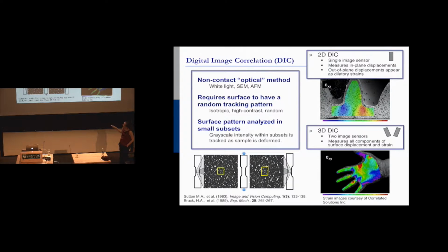So it starts out square, and then as you pull and you continue to take images through the test, the box is going to change its shape. And you do that for many, many boxes that are overlapping, and you minimize some cross-correlation functions, and you can get a very, very accurate full-field strain on the surface of the specimen. And so if you do 2D, that's one image and one specimen and one camera on the specimen. The problem with 2D is everything has to be planar, because the minute that you move your specimen towards the camera, the dots look bigger, but I haven't actually applied any strain, right? It's just a rigid body displacement. So you have to be very careful about 2D, keeping things in plane. If you do 3D DIC, you actually have 2 cameras on the specimen, and you can measure out-of-plane displacements.